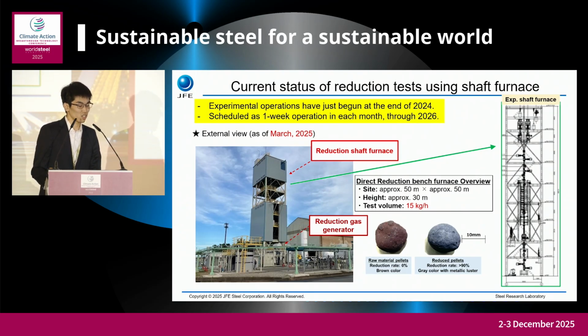Operation began at the end of 2024, and we have successfully produced DRI consistently using low-grade pellets and 100% hydrogen. We will continue to identify optimal reduction conditions for each property of low-grade raw materials, primarily using blast furnace grade pellets. And we also continue to develop direct reduction methods using carbon recycling technology.